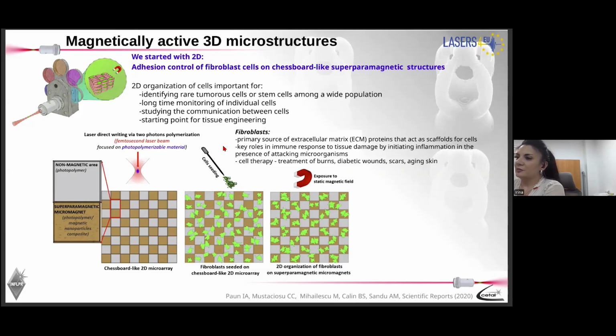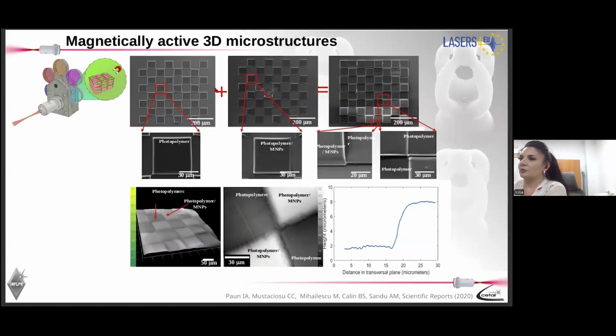If we seeded fibroblast cells on this chessboard-like structure, without any kind of magnetic field around, the cells attach randomly all over the place. On the opposite, when we place the chessboard-like structure in the static magnetic field, the cells preferentially attach on the magnetic squares. This is the design of the experiment. This is actually what we did.